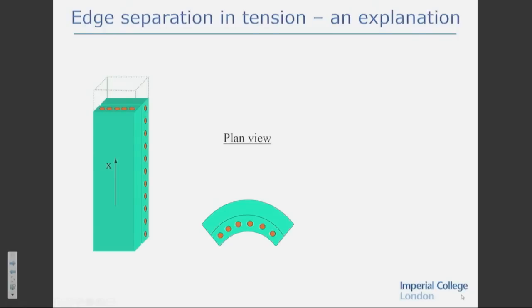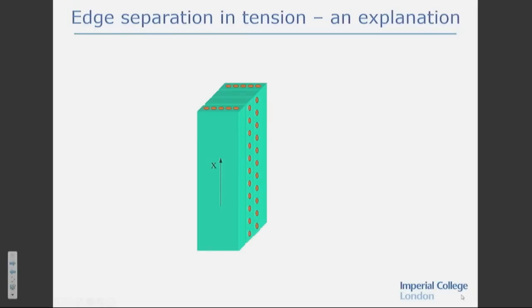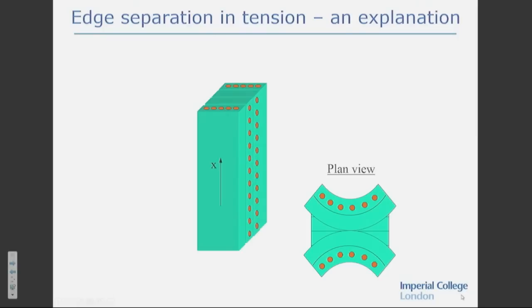And so in plan view, that on its own, subjected to an axial strain, would deform like this. And then remember that this specimen actually comprises a symmetrical unit at the back here, exactly the same as the front one. And therefore, when we look at the plan view of this, we know the two halves are trying to do this. And it's exactly this problem where the two halves are trying to curve apart, which starts pulling it apart at the edge. And what we have during that test is that separation advancing towards the middle. And the material property that controls how that separation progresses inside the specimen is the separation resistance.